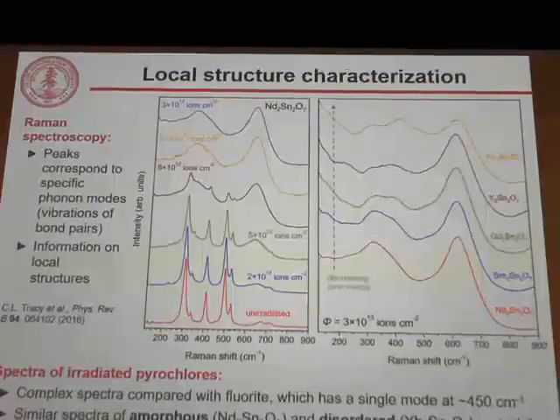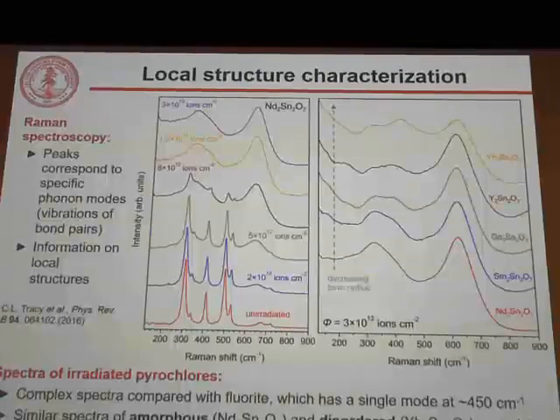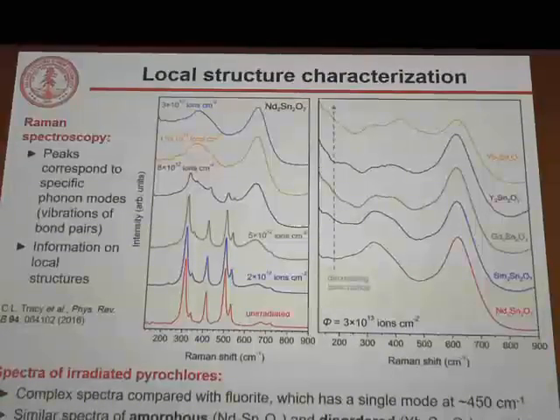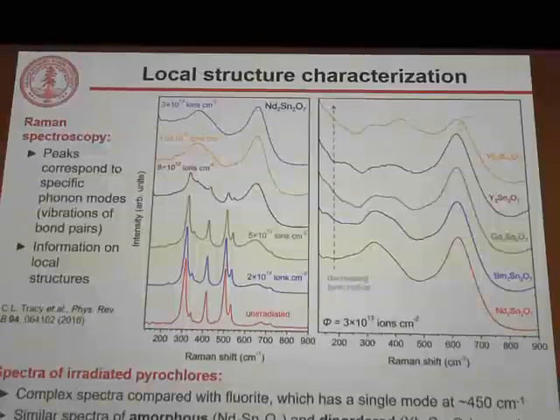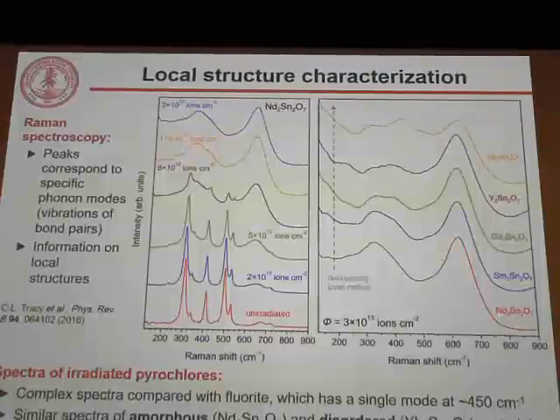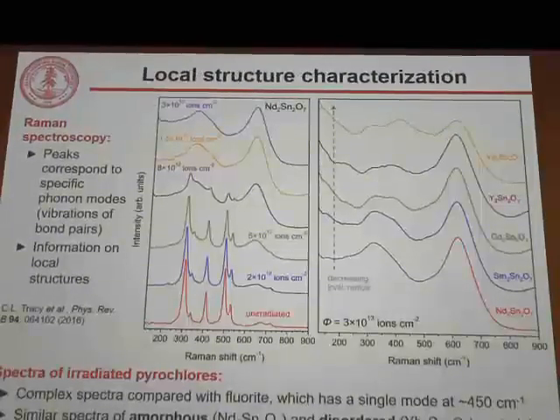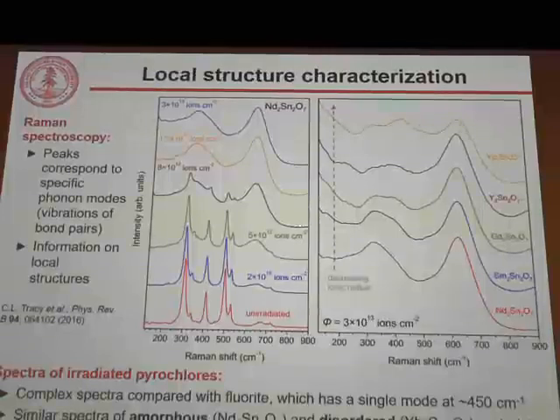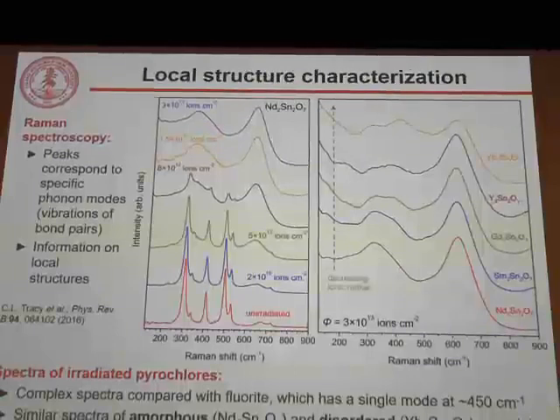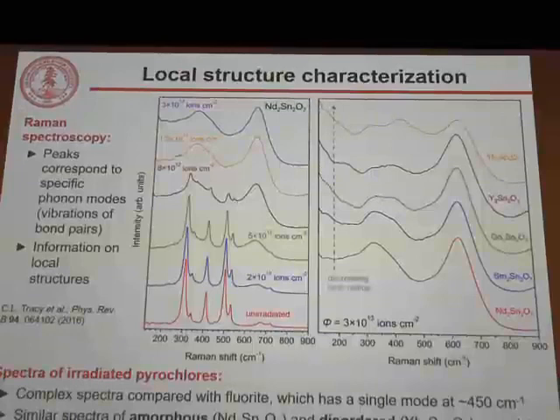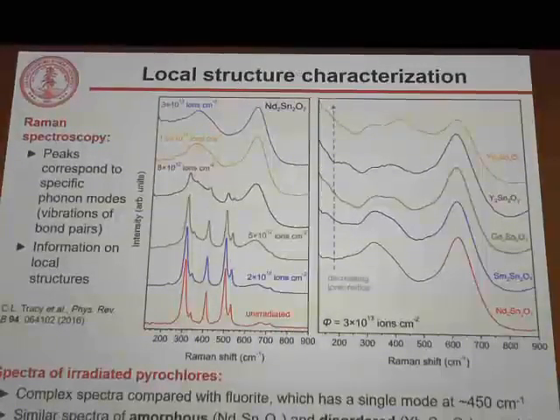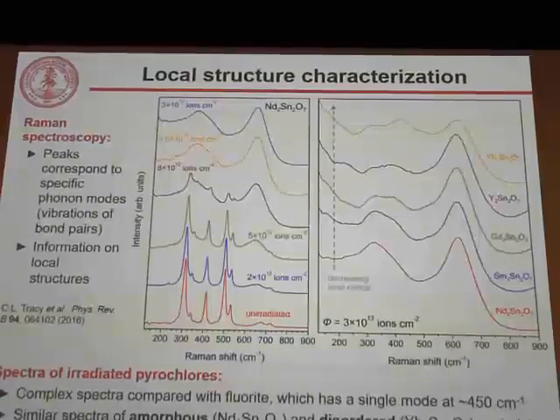But if we compare the high ion fluence, so the heavily damaged, Raman spectra of a lot of different pyrochlores, remembering that some of them, like neodymium stannate, according to XRD, are amorphous, whereas others, like ytterbium stannate, according to XRD, are still crystalline, just in this disordered fluorite structure, we have some interesting observations here. First of all, they all have very complex spectra, none of which are consistent with a fluorite local structure, which only has a single Raman mode. Second, we have almost the same spectra regardless of whether, according to XRD, these materials are amorphous or whether they're simply crystalline yet disordered fluorites.